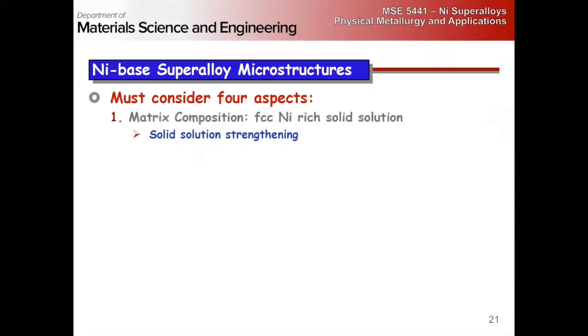So for superalloy microstructures, we have to think about a couple different aspects when trying to describe the grain structure. In the gamma phase itself, we have solid solution strengthening, right? We're trying to maximize strength here. If we're going to create a lot of gamma prime, we don't want to leave a very weak matrix behind. We don't want these difficult to cut particles in a phase where we can have lots of easy plastic deformation. So we want to maximize solid solution strengthening in the gamma phase, okay?